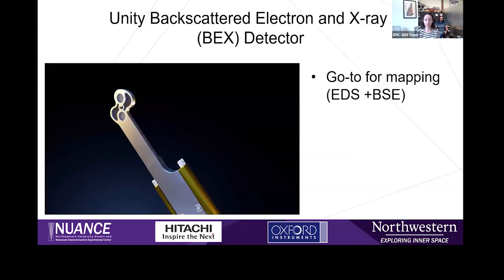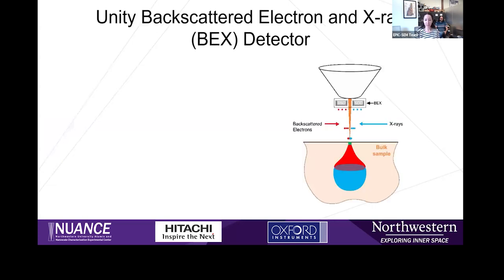So last up on our EDS detector tour is the Unity BEX detector from Oxford, and this is the world's first backscattered electron and X-ray detector. This is going to be your go-to if you're really interested in compositional mapping, and this will do both EDS and BSE mapping. This detector is actually placed directly underneath the objective lens, so it simultaneously can collect BSE electrons and X-rays with a large solid angle for those high count rates.